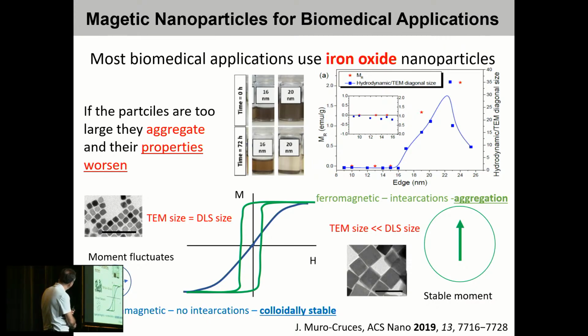As the base state, they are colloidally stable. If we make them slightly larger, like 20 nanometers, in the base state, they are also colloidally stable. But if we wait a few days, the 16 nanometers, they are still stable. But the 20 nanometers ones, they precipitate. What happens is that with time, they agglomerate. We can see this very, very clearly.